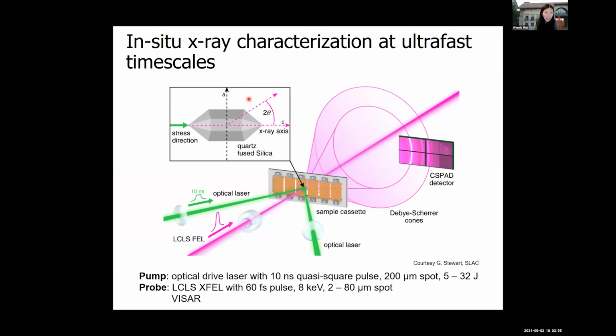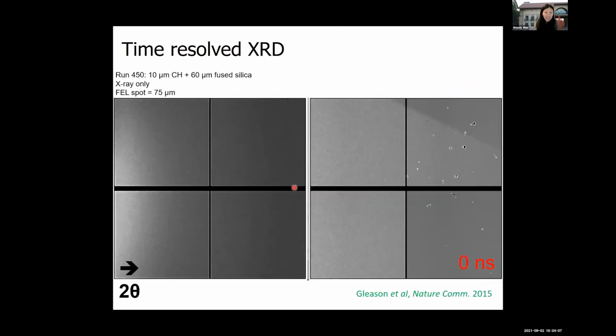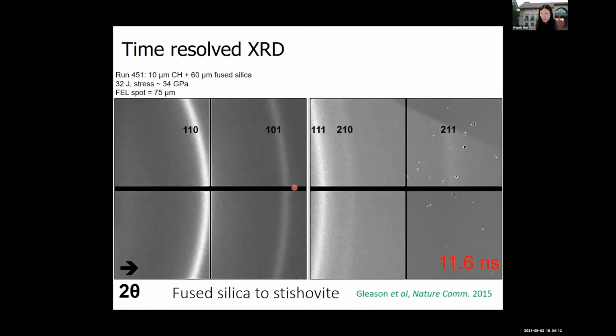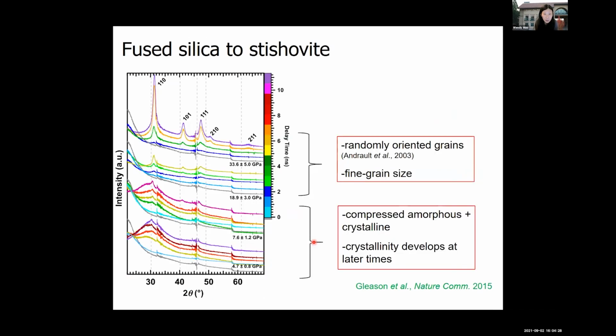And so this is a study led by Ariana Gleason, where she looked at how silica changes as the shock propagates through it. Okay, so these are just at 0 nanoseconds, no shock. It's a silica glass, so you don't see any diffraction pattern. And then 11.6 nanoseconds later, the shock is in the sample, and you can see that you've crystallized stishovite. And so you have these smooth rings that correspond to octahedrally coordinated SiO2. And then you can integrate many patterns at different laser powers over different time delays to get information on grain growth and phase transitions in silica.